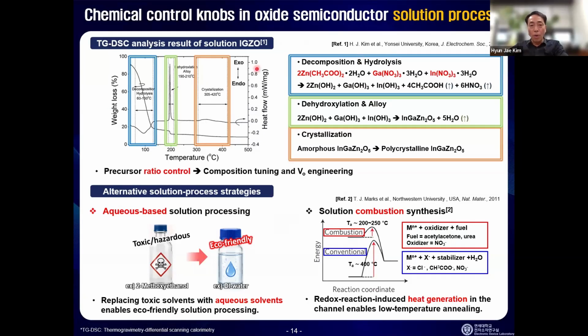Oh, this one is a little bit old. You know what? People try to use not the expensive vacuum system. They try to use solution-based. You know, they have acetate and nitrate and all this solution-based material. Okay, you heat it up, boom, weight goes down because the solvent is going, right? And then in this range, heat it up, right? So dehydroxylation and alloy. This is the part where the material forms, okay? And then if necessary, you can do the crystallization.